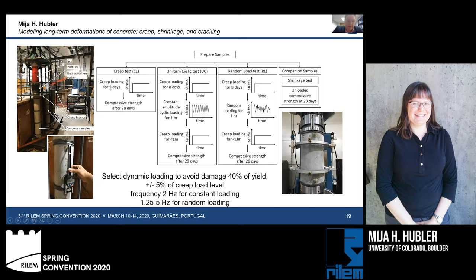In the first track here, we'll call this the creep test track, we simply apply a constant stress over time and observe the evolution of the strain, and test the compressive strength after 28 days. In the next parallel track, called the uniform cyclic loading track, we do the same thing. We conduct a creep test, but we then interrupt it with 1 hour of constant amplitude cyclic loading. After the cyclic loading, we continue the creep test and run a compression test to see if there is an impact due to the constant amplitude cyclic loading. Then we also have a parallel track where we do the same thing for random loading for 1 hour to test what the impact might be on the long-term behavior. And finally, we have companion shrinkage tests and samples to assess the impact of the environmental effects.